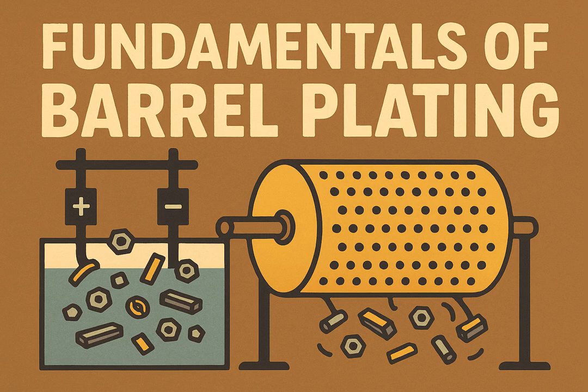Okay. And what about problems after plating? A particularly frustrating post-plating issue, often seen with barrel-plated parts processed in bulk, is spotting out. This is discoloration or stains that appear on the plated parts hours or even days after they've been plated and stored. Looks fine initially, then stains appear later. Delayed problems. What causes that? It's frequently caused by tiny traces of process chemicals, like cyanide from certain pre-treatment dips or copper strikes, that weren't completely removed during rinsing and got trapped on the surface, especially in recesses or pores. When parts are stored in bulk and aren't completely dry, these residual chemicals can react with the air or moisture and cause staining over time.